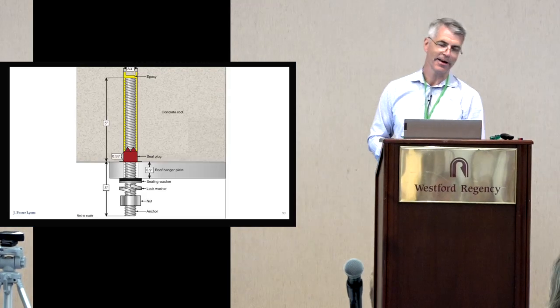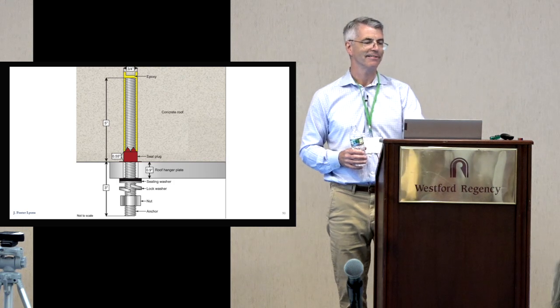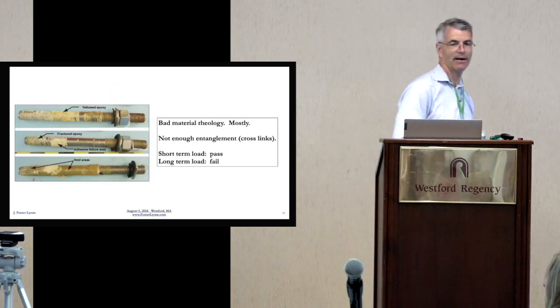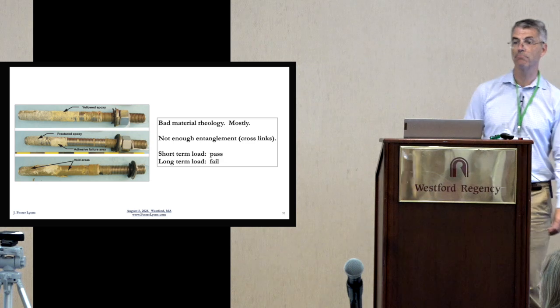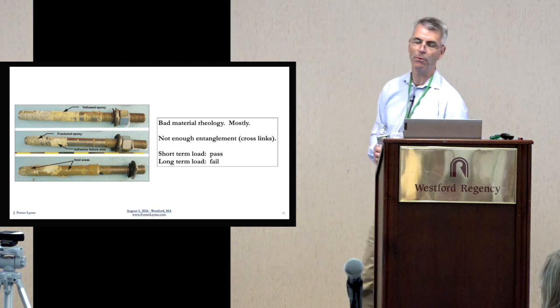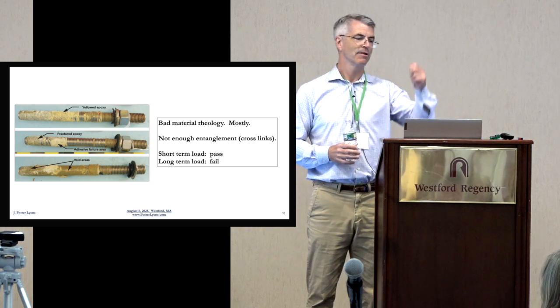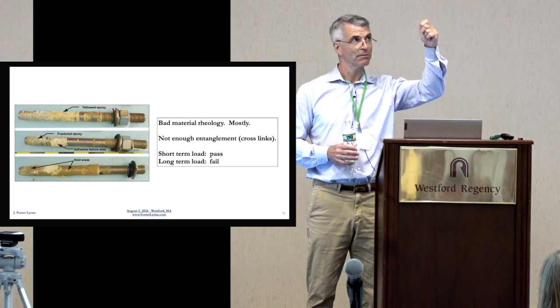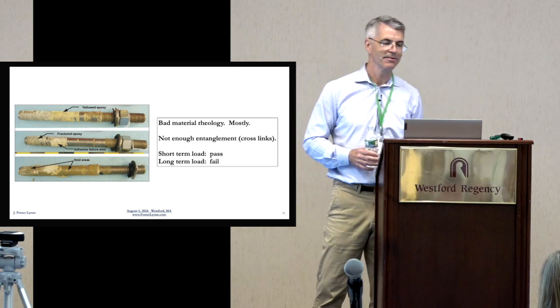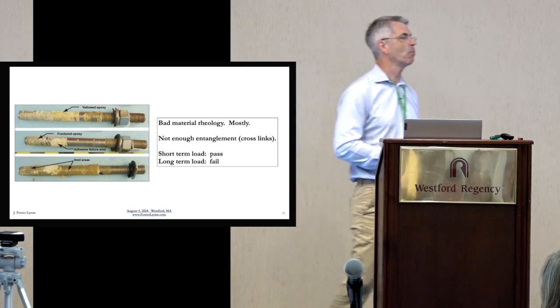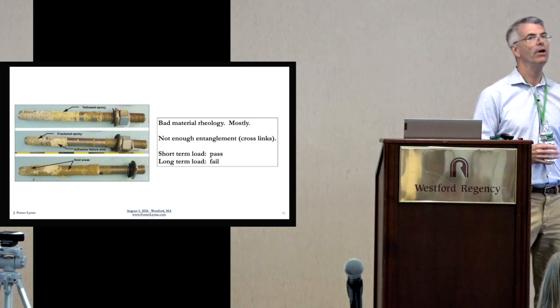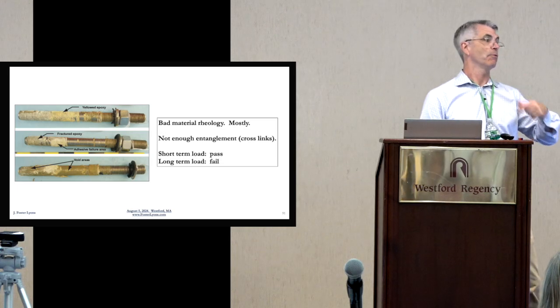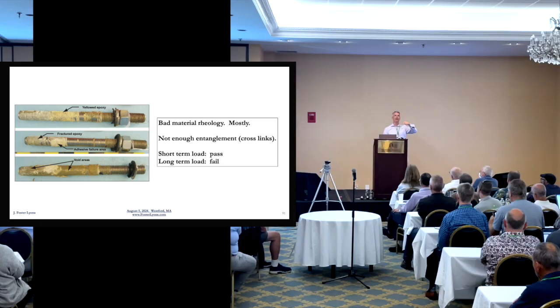So this is just an image. It's just a bolt into the concrete. And these are images of them after the fact. They just pulled out. This was bad material rheology, mostly, okay? Very slowly over time, the bolt came creeping out, and they have pictures of this. The short story is there just wasn't enough of what I'm going to call rigid entanglement. There was plenty of entanglement, but it was able to very slowly relax over time. And that was enough to allow the load of these concrete ceiling panels to pull the bolts out.